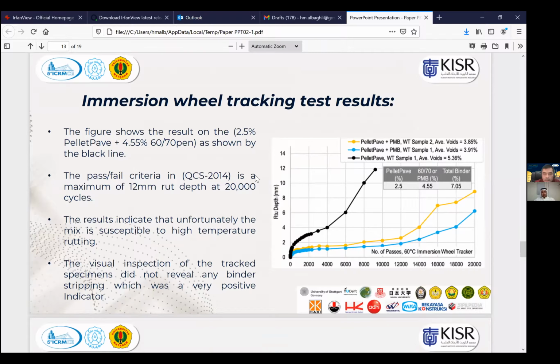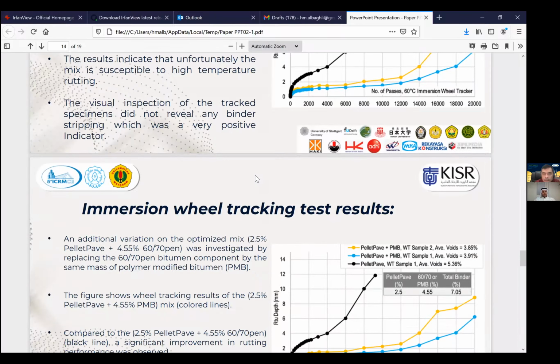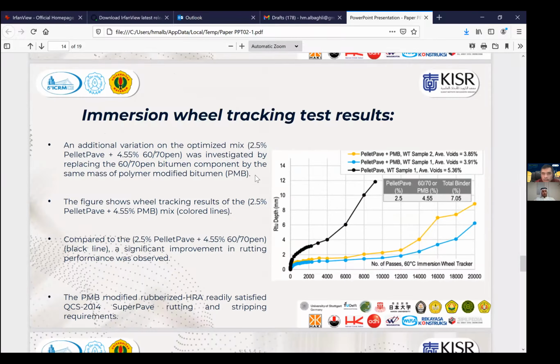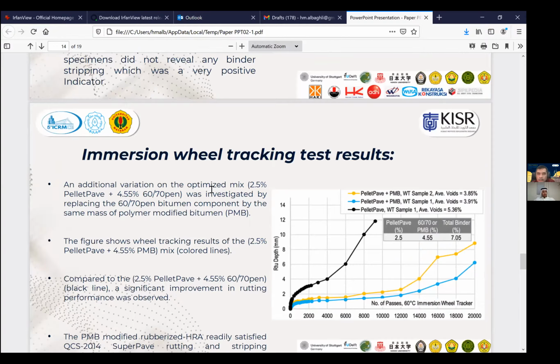As a result of this failure, we investigated an additional variation on the optimized mix, the 2.5% plus the 4.55%, by replacing the 60-70 bitumen component by the same amount of polymer modified bitumen. The objective was to assess the capability of Pellet Pave mixes to be designed for heavy traffic roads. We carried out another wheel tracking test at the same parameters and the tensile strength ratio (TSR) in compliance with T283.